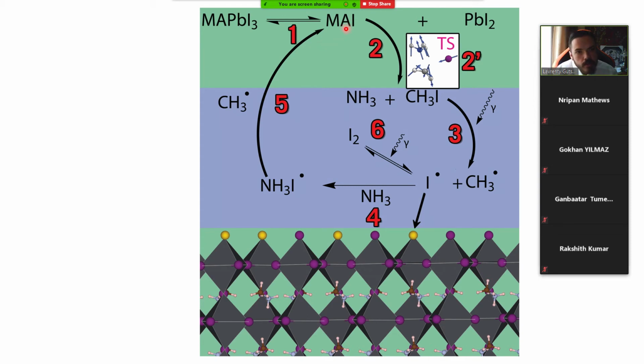basically restore methyl iodide. And that is basically why methylammonium lead iodide is so unique, because it goes through this gas healing process, and actually the gamma radiation aids it in self-healing itself. And other perovskites simply do not go through this gas phase chemistry, and that is basically why this happens.